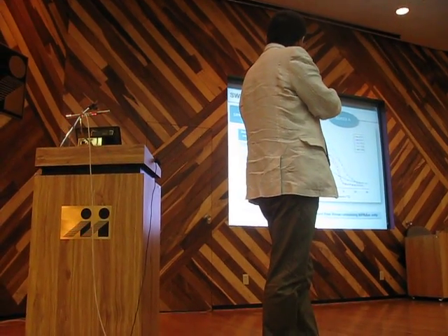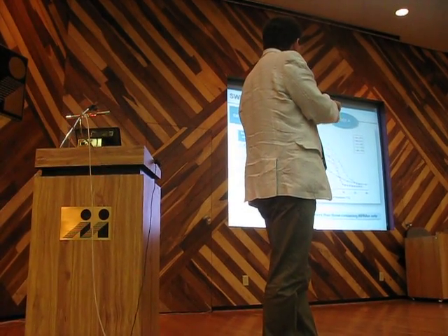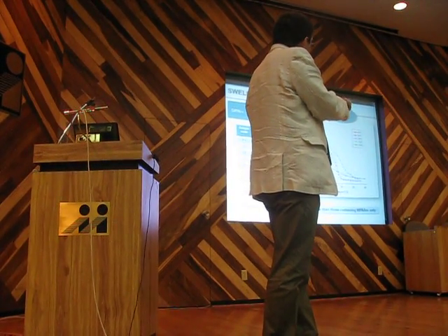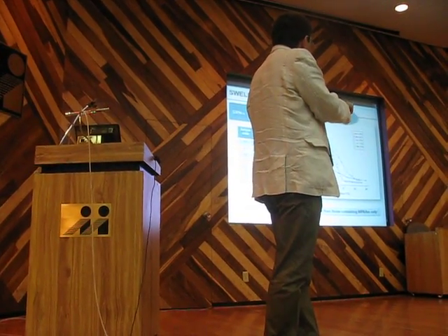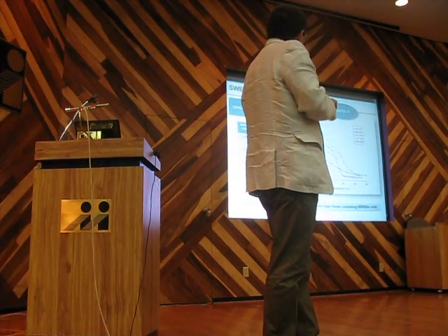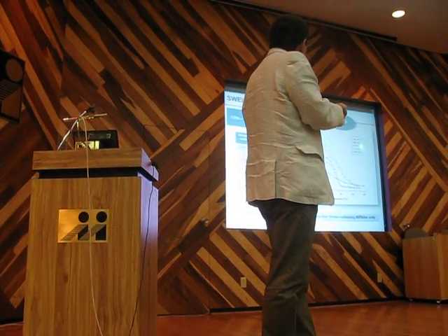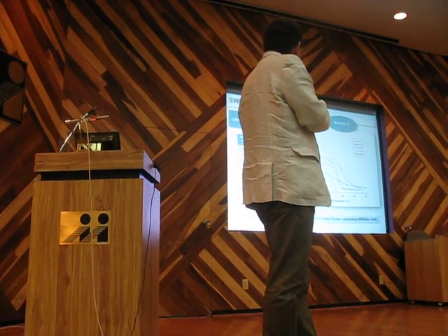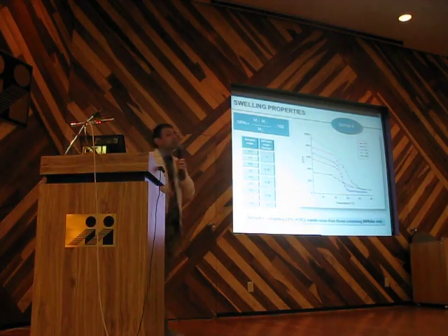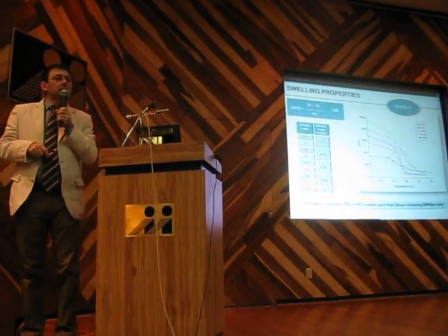These are those referring to polyNIPAM, the other homopolymer, and you can see the swelling ratio is higher than that of poly(vinyl caprolactam), and the sharp transition at about 28-30 degrees. Okay, but the copolymer with, you can see F2, 75% of NIPAM, 25% of vinyl caprolactam, swells even more than what the polyNIPAM does.